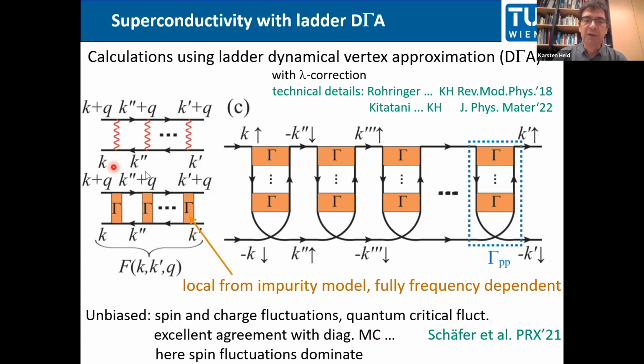What we do here now is we go one step further. That is like a first step in a more fully Parquet approach. We take these antiferromagnetic spin fluctuations and go to the next channel, that is the particle-particle or Cooper channel where superconductivity lives. So this way we describe how antiferromagnetic spin fluctuations or magnons mediate superconductivity in our system. Maybe I should emphasize that we also describe charge fluctuations and other fluctuations on an equal footing. Just for the nickelates, the spin fluctuations are dominating, and we get d-wave superconductivity mediated by antiferromagnetic spin fluctuations.